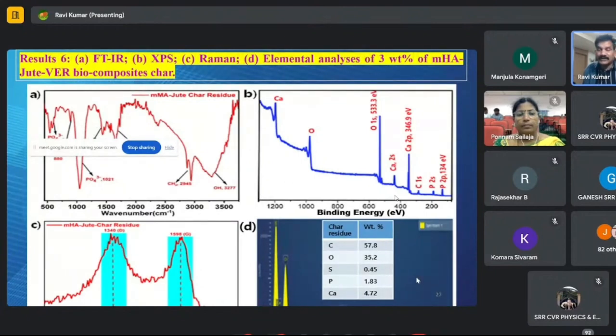Also, the elemental analysis shows phosphate and calcium, almost 4.72 for calcium, phosphate almost around 2, and carbon is 57.8%, oxygen is 35.2, and sulfur is 0.45. This is generated from the other materials. And you can also see the MHA jute char residue, XPS, and Raman. The Raman peaks show the char has a D peak at 1340 and a G peak at 1596. These two signals are very important to identify the char. So XPS, Raman, and FTIR strongly show that our material is good enough to protect the targeted fabric and targeted panel.